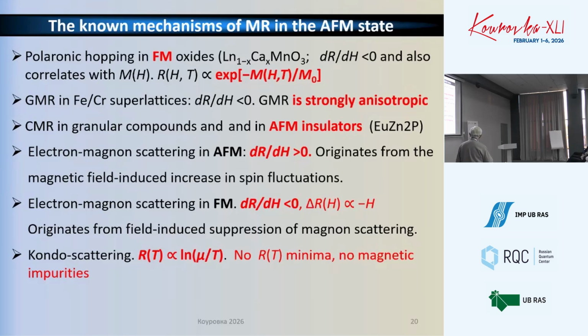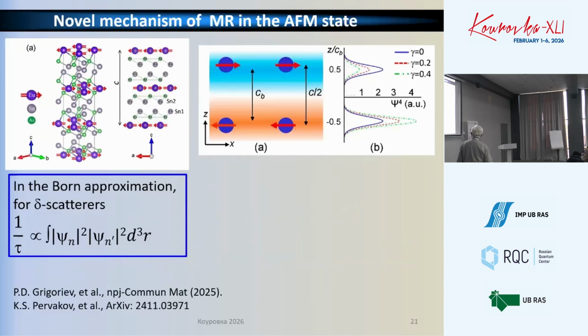And I stressed and showed the data that the effect which we want to explain is isotropic. And isotropy immediately prompts us to consider the simplest point-like scattering. Point-like scattering is always present in the material because the resistivity doesn't go to zero. But what happens when the electrons propagate in an alternating environment with alternating direction of magnetic moments of europium layers? They tend to redistribute in real space. Here with the colors orange and blue is schematically shown how electrons try to redistribute in real space. Some of them which have a spin parallel to europium atoms move to this layer and others move to this layer.